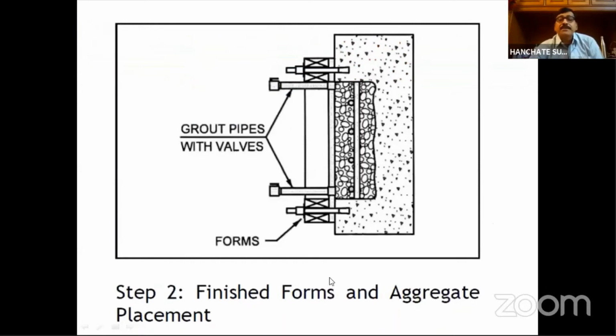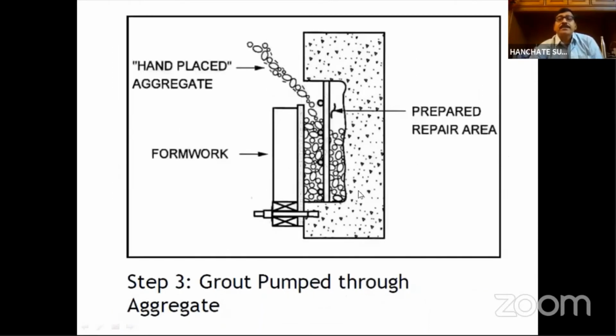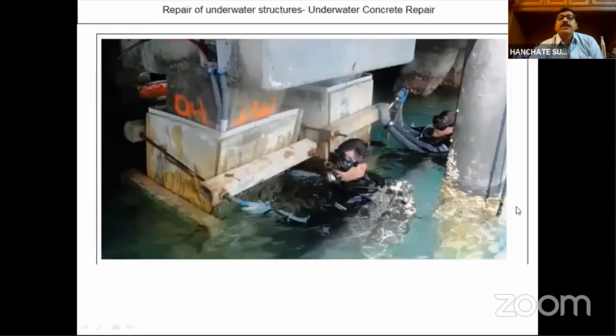The second phase is we finish the forms and aggregate placement. So here you can see all the aggregate placement is completed, and the formwork and the grouting pipes are installed here. So this is the second step. And the third step is pumping the grout through the aggregate. So this is the aggregate. Now the cement grout is pumped through the aggregate. So this completes the repair for this damaged zone. So these are the three steps which are used in underwater concrete repair.